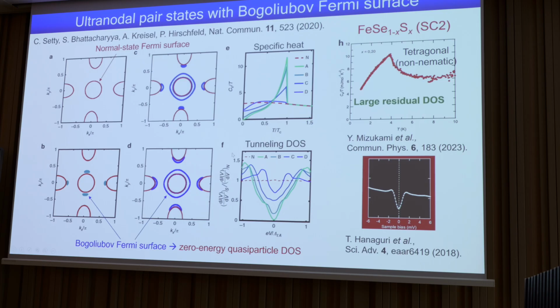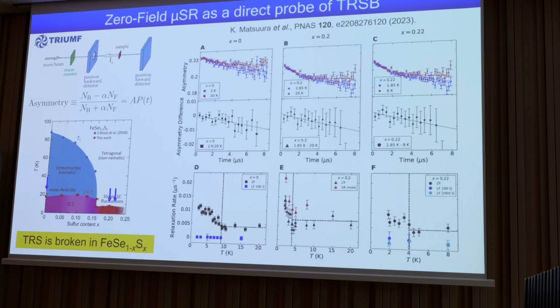So we decided to collaborate with Tomo Uemura to look at the zero field μSR, which is a very sensitive probe of the magnetic field inside the sample. This can be used as a direct probe of time reversal symmetry breaking.